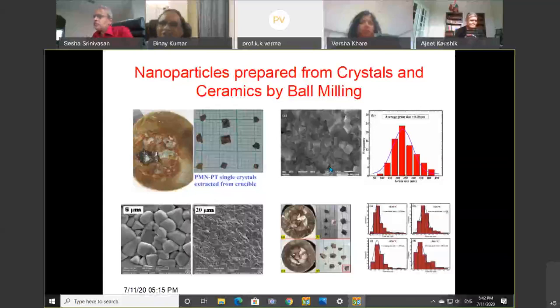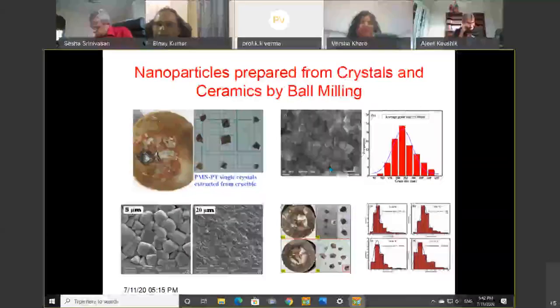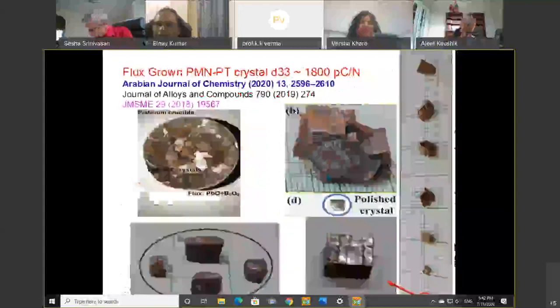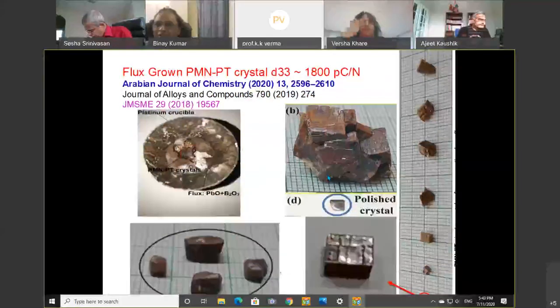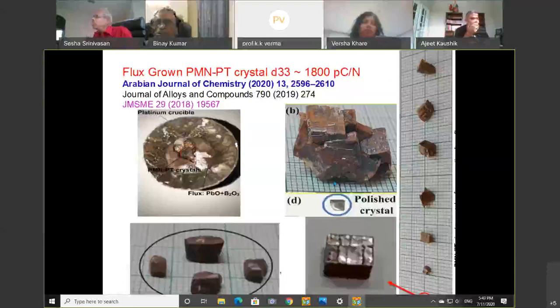This is another crystal, PMN-PT, which we have used as a crystal also. We have used them to crush and get nanoparticles of PMN-PT. These are the highest values of D33, almost close to 2000 picocoulomb per newton. It means it is almost 1000 times more efficient than normal quartz crystal.